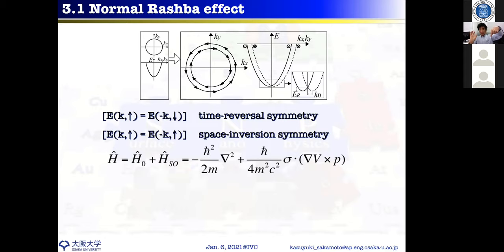We also found that at K points with C₃ symmetry — the same symmetry as the gamma point — even without space-inversion asymmetry (which was believed to be a necessary condition for Rashba), we observe Rashba-type spin splitting. The C₃ symmetry can explain this analogously to the gamma point. Our group has systematically studied how different symmetries, including C₁ₕ symmetry, can create non-collinear spin structures where spins point uniformly along the -Y direction on one Fermi contour and +Y on another — a non-vortical spin texture.